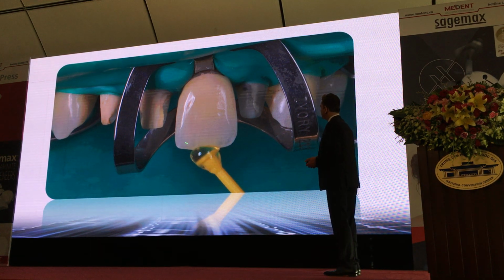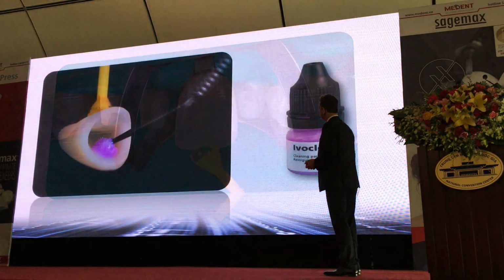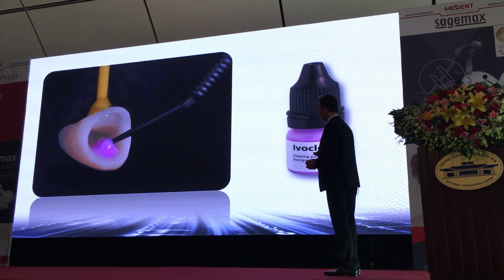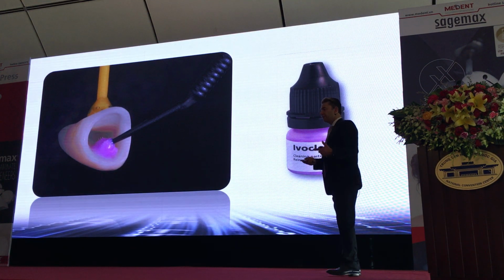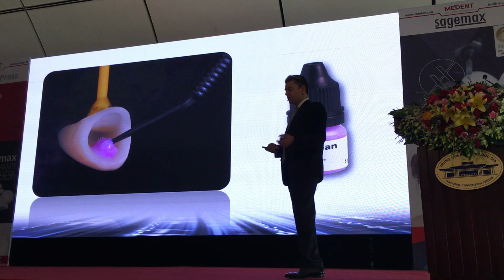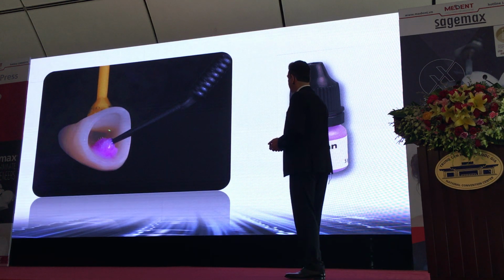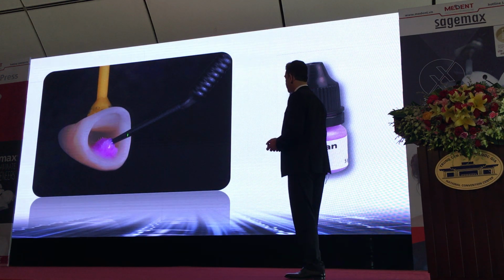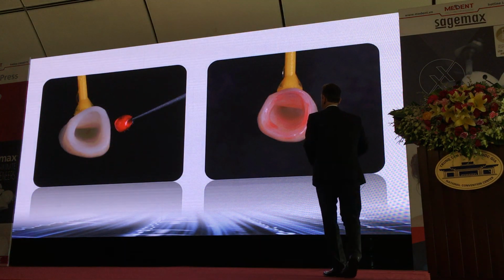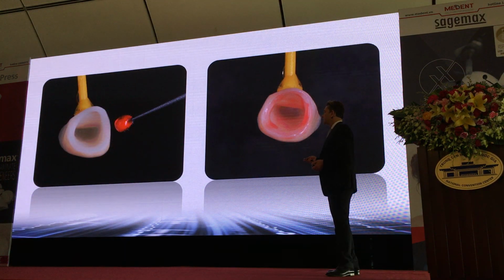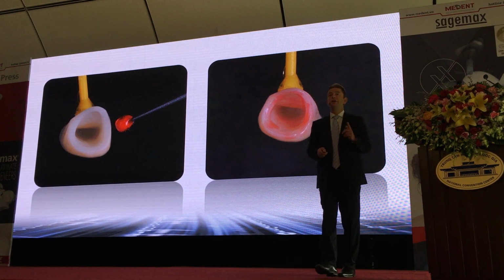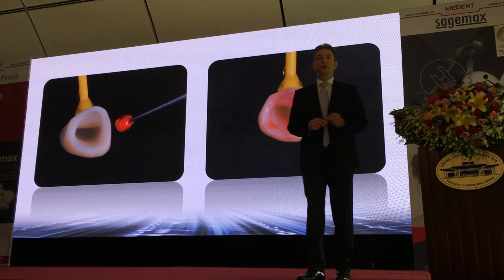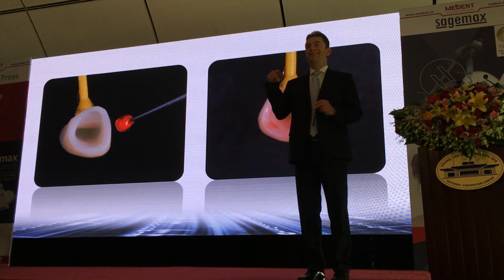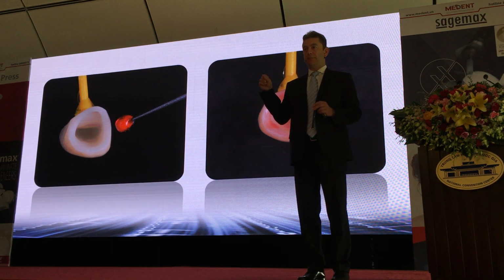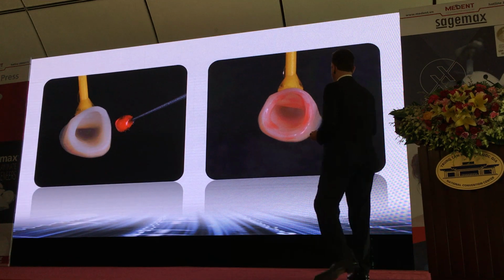Yeah, you can see here, this is one of the crowns. When you do a try-in again, if you want to do a try-in after your preparation, after etching and everything, then you need to use IvoClean, because then you get rid of the contamination. Okay, now we can use hydrofluoric acid. If you use hydrofluoric acid for emax, it's always 20 seconds. Yeah, 20 seconds application of hydrofluoric acid.